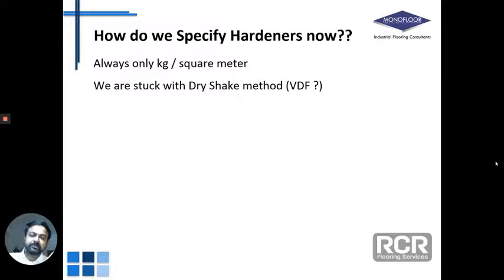these cementitious hardeners, when using a dry shake method, depend on the water available as a bleed on top of the concrete surface to hydrate. So this water is needed for the hardener, whereas during vacuum dewatering, you are trying to remove this water away from the surface. So basically, you can safely assume that vacuum dewatering is not a very compatible method when it comes to the dry shake hardener.